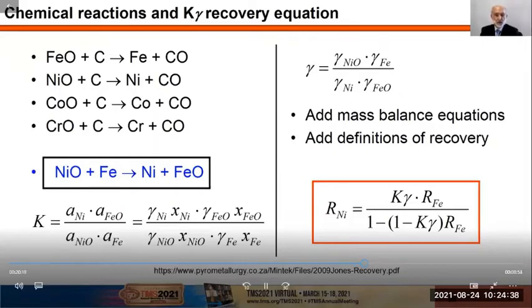If you combine the first 2 chemical reactions, you effectively result in the exchange reaction highlighted in blue between nickel oxide and iron, forming nickel and iron oxide. For this reaction, the equilibrium constant K can be found in tables at a particular temperature, and the equilibrium equation can be written in terms of the activities of the various reacting and product species, as well as the activity coefficients gamma and mole fractions X of those species. For convenience, we can lump together all of the activity coefficients into one term, just a number, called gamma.